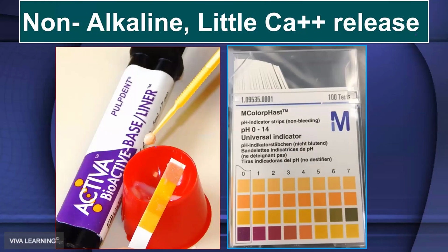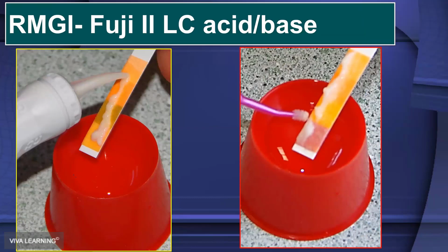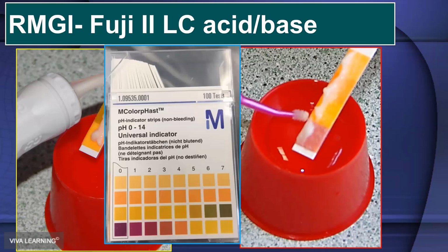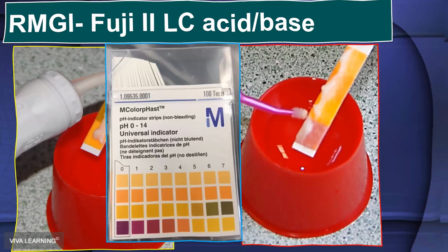And then you can look at a base liner here from Pulpdent. You look at the pH of that. You go, wow, that is around 3. Well, that's not alkaline. That's really acidic. So that is really more like a glass ionomer. In fact, if you do Fuji II LC, you end up with the same pH, around 3 to 4, more toward 3, probably around 3.4 is what Fuji II LC is in the literature. So that's acidic. That does not encourage remineralization. That doesn't encourage more reparative odontoblastic formation. It just doesn't encourage that.